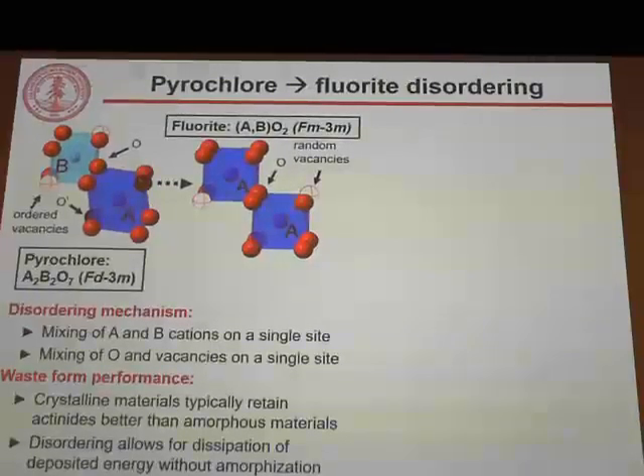And this is, as I mentioned, important for waste form performance, because crystalline materials tend to retain actinides and immobilize them better than amorphous materials. In crystalline materials we maintain the local bonding of a radionuclide, such that it is held in place and is less susceptible to leaching by groundwater, for example. So this disordering mechanism allows the energy deposited by radiation, by decay heating, by pressure to be dissipated without losing the crystallinity of the material, so that we can expect it to retain its nice immobilization properties.